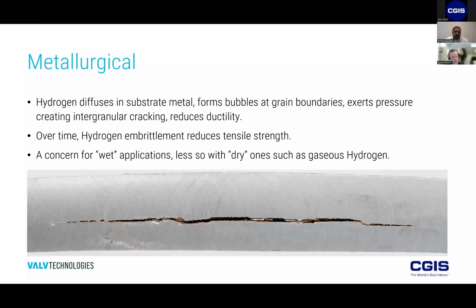Thank you. And the last question: with the valve so tightly sprung against the seat, will the valve ball seat surface also wear much quicker? So that's where the coating comes into play, and the coatings are there to protect the valve components as they cycle. Even if you just took a valve and cycled it 100,000 times, which we've actually done in the laboratory, and then took it apart, it can be shown that there's very little wear even after 100,000 cycles.